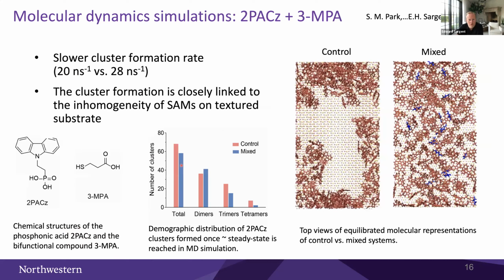In further MD studies, when we contemplated the addition of a new component, 3-MPA, in combination with the phosphonic acid, we found a trend wherein it appeared that we could reduce the concentration of the clusters, or reduce the propensity to form clusters. You can see this in the top view over here. You can see the clustering on the left in the control case with just the phosphonic acid, and the improved uniformity projected in MD with the mixture.